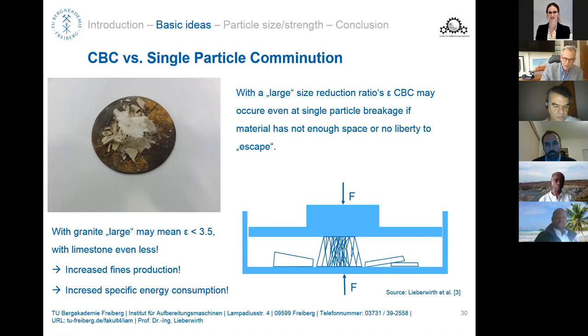People are not even thinking about confined bed comminution, and still they are into this. So in this single particle comminution, we already achieved the confined bed situation, or this caking, at reduction ratios of less than 3.5. Now think about what we are talking about in many primary crushers, like jaw crushers, cone crushers, or others. We are at reduction ratios of 5. Of course, not in one step, and this is also an important point, whether you achieve a certain reduction ratio in one pass or in several passes.